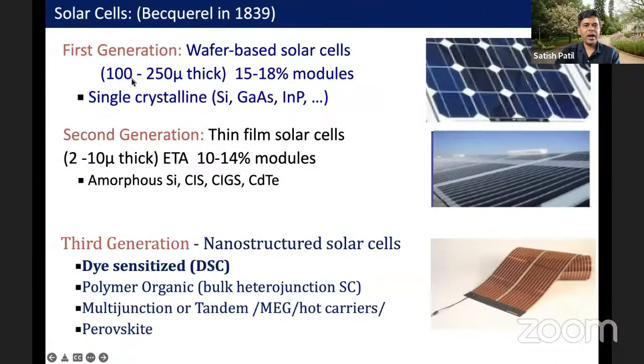You use a 100 to 250 micrometer thick film when you use single crystalline silicon. When you use amorphous silicon, you use a thinner cell, because single crystalline silicon solar cells are an indirect band gap material. It's a lousy material for light absorption. Its absorption coefficient is very small compared to amorphous silicon and other materials.